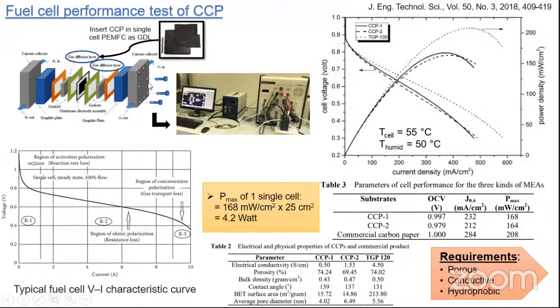As I mentioned before, we have this instrument to check the performance of GDL in PEMFC stack. We get an IV curve, and we can summarize that our composite has a current density around 232 milliampere per centimeter square. It's close to the commercial carbon paper. So we can summarize that our composite is successful to apply as GDL in PEMFC.